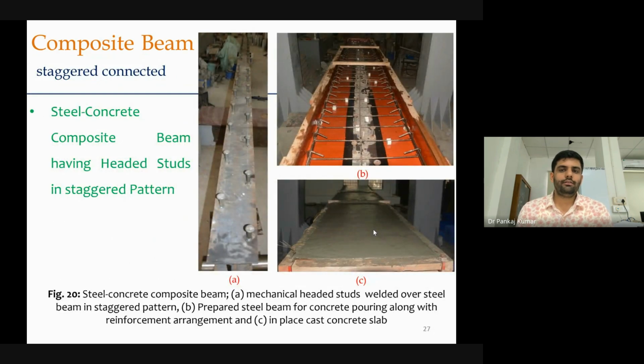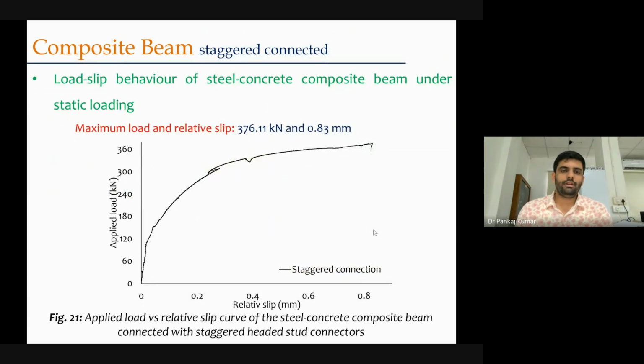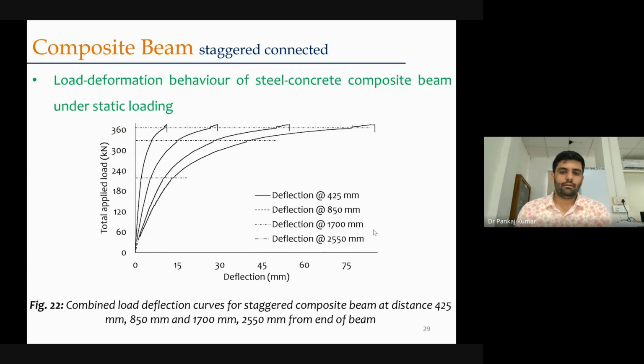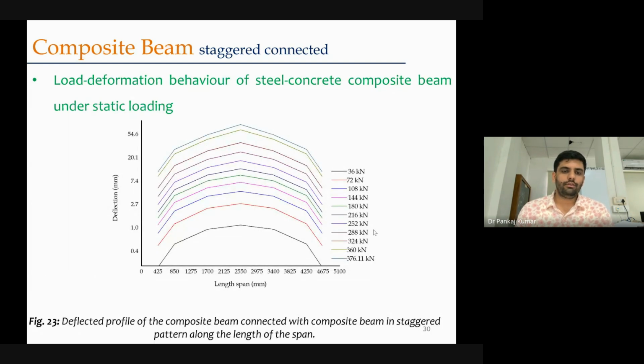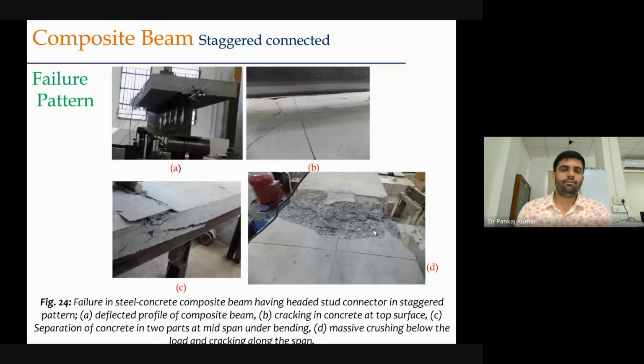Then the next pattern is about arranging the studs in a staggered pattern. In the last case the connectors were arranged in a line pattern; now it is a staggered pattern. For that we also measured the ultimate capacity as well as the relative slip at the interface level and deformations. In a similar way, we drew the deflection at the different locations along the entire length. We put all the LVDTs on one side, only the slip we took on both sides, and then we replicated half of the behavior because the beam was symmetric with respect to the central axis.